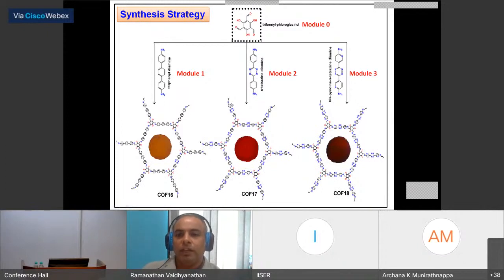So how do we achieve it? We use module zero, which is the trialdehyde, which has three OH groups in it. And then we are going to systematically change module one, module two, and module three, where the difference is, here it is all carbon. Here we use a tetrazine unit, which is more electron withdrawing. And then here, we use a tetrazine unit along with a pyridine group in a very systematic manner. And this is now an electron rich center. This is an electron deficient center. So you will have a push-pull effect going into the structure. So thereby you can see how you can alter the HOMO-LUMO levels.